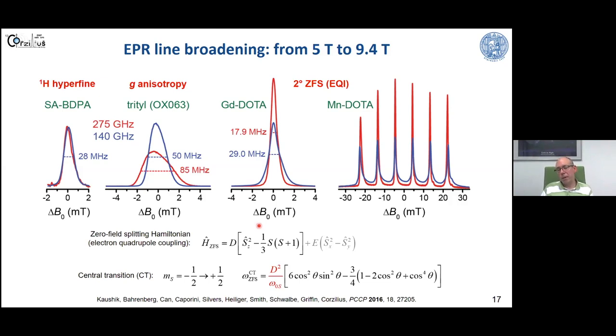electron sitting inside your electronic system, occupying practically the whole molecular orbitals. And this means that typically the excitation energies of this single electron into higher states are rather small, and this energy separation to higher states is rather small. And then you have a significant admixture of these excited electronic states, which causes a typically rather large g anisotropy. For example, if you look at copper 2 plus, you have a typical g anisotropy between 2.04 or something like that, or 2.1 to 2.4. This is like a 20% g anisotropy, and you usually don't even have any resonance at g equals 2 if you neglect the broadening or so at high field.